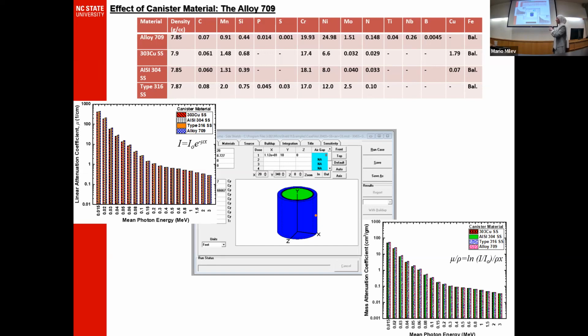So what we observed when comparing 709 and other stainless steel is that 709 exhibits a higher attenuation coefficient, which means it has better shielding properties than the other common stainless steels used as canister material in spent fuel dry casks.